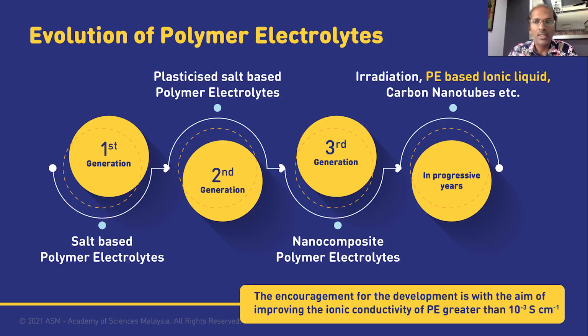First generation polymer electrolytes, also known as salt-based polymer electrolytes, even though the conductivity is enhanced, but it is not sufficient to be applied in high-performing devices. To overcome this, we introduce second generation polymer electrolyte, the plasticized salt-based polymer electrolyte, which can further increase the ionic conductivity, but the mechanical property deteriorates. The third generation polymer electrolytes are nanocomposite polymer electrolyte, which increases the ionic conductivity, improves the mechanical property, and the aging effect of the system. In progressive years, there are many other methods like irradiation, polymer electrolyte-based ion liquid, and carbon nanotubes were explored.